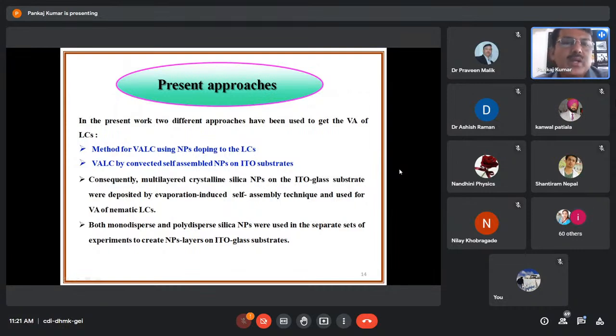So consequently, multi-layered crystalline silica nanoparticles on the ITO glass substrates were deposited by the evaporation-induced self-assembly technique and used for the VA of nematic LCs. Both monodisperse and polydisperse silica nanoparticles were used in separate sets of experiments to create a nanoparticle layer on the ITO glass substrates.